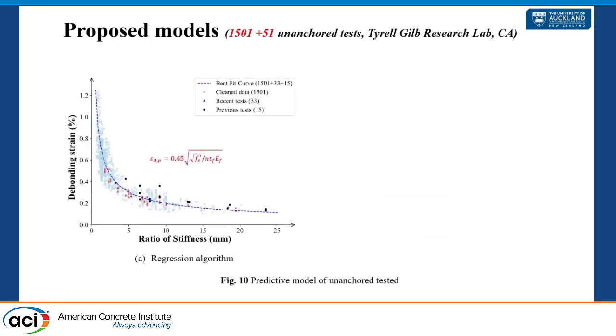Then, based on our hypothesis and what inspired us, we proposed our first model, the predictive model. We initially plotted a scatter plot of debond strain against the stiffness ratio of FRP and concrete, but we found a nonlinear trend there. So we used the Tukey fence method to remove the unreliable outliers, then used a regression algorithm to get a best-fitting curve. Then we got this nonlinear power relationship for our predictive model.